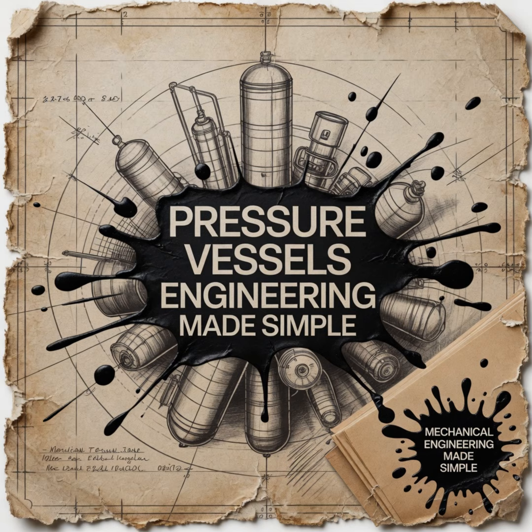But arguably the most dangerous defect of all is lack of penetration, particularly at the root. The root is the very first pass, right? Yeah. The bottommost layer of the weld. Right. Often on the inside of a vessel where it's incredibly hard to see. So what happens if they miss the root? When you bevel two thick plates to form a V-groove, the root is the narrow gap at the very bottom. If the welder's arc doesn't penetrate all the way through that gap to melt the bottom edges together, you are left with a sharp, unwelded linear notch running along the inside of the vessel.